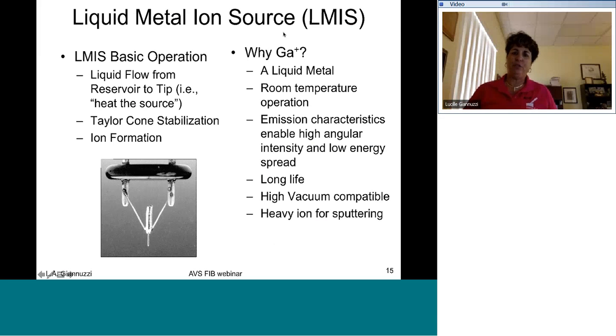So the liquid metal ion source has pretty much been the standard over the past 2 decades or so. Basic operation of how this works: this is the source itself. Basically, you have a tungsten tip, and the tungsten tip sits on this coil for a reservoir, which is also conductive. You've got these conductive wires that lead to this ceramic non-conducting material. So current flows through one way into the other. The current heats up gallium, which sits in this little reservoir. Gallium is nearly liquid at room temperature, so you don't need to turn up the current very high in order to turn this solid gallium into a liquid.